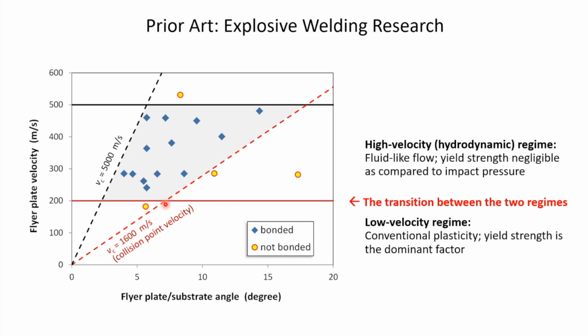But there was another boundary, and that was the more interesting one for me, and that was the boundary between what is called the high velocity hydrodynamic deformation regime. So that's what's happening in explosive welding, actually manifested by a jet of material flowing out of the interface, and the normal low velocity regime, which is like conventional classic deformation. So the transition between the two is something that we thought might also be relevant for cold spray. But in cold spray, we have a problem because the angle between the substrate and the flowing object is not constant, because normally you have a sphere. So a very subtle complexity coming from the geometrical considerations. So that was the difference. So with these in mind, then we started the research.